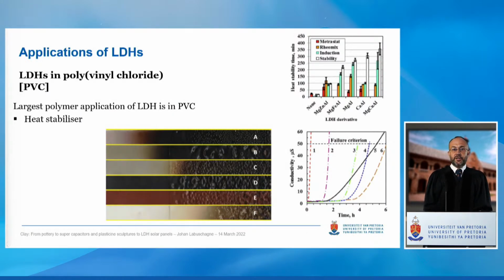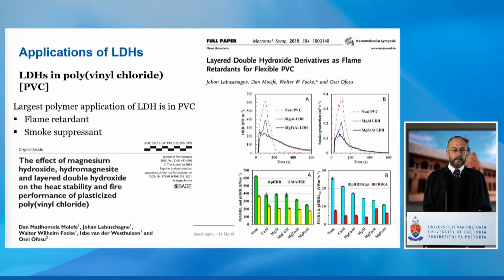Right-hand top, I show the neat material, the neat PVC, with the different LDHs for different stability tests that we conducted. And you can see that the stability typically increases and drastically increases with LDH. Right-hand bottom, just another graph showing another static test.